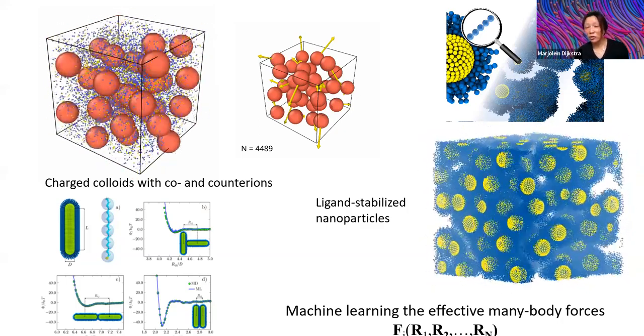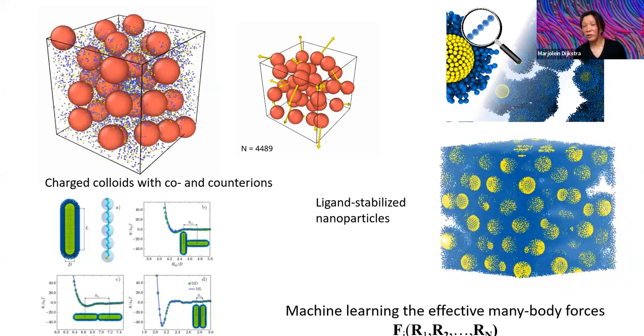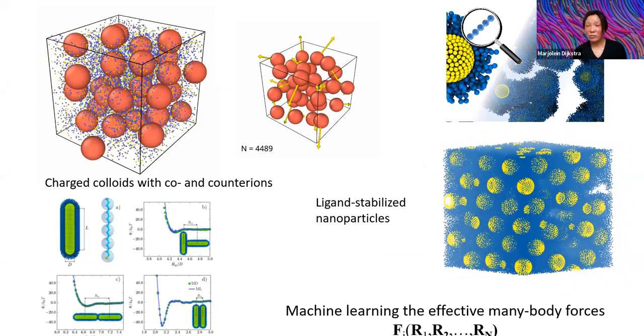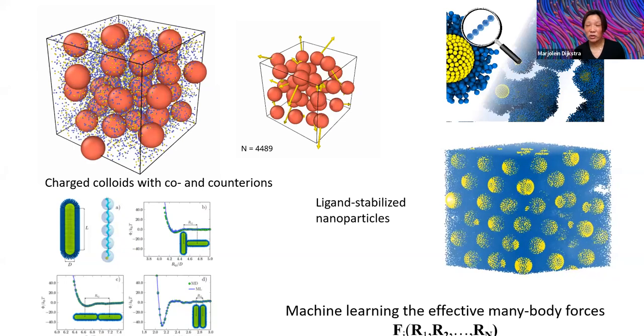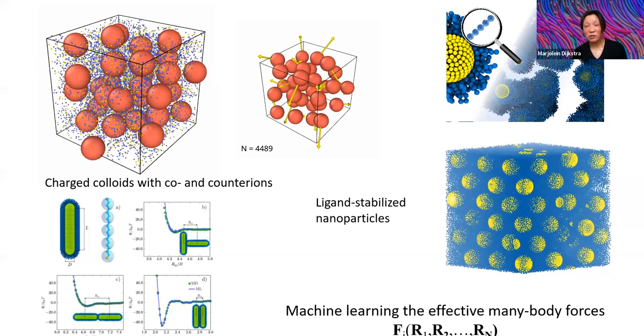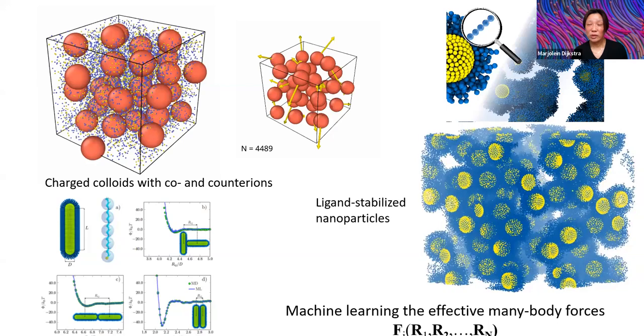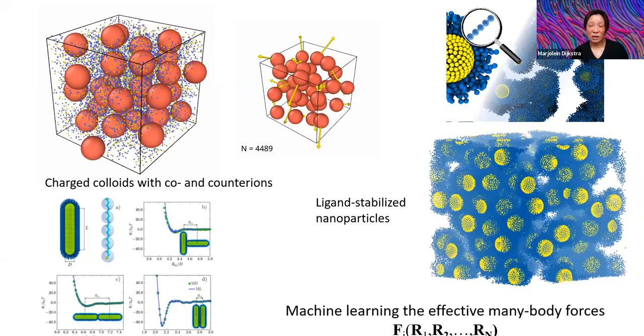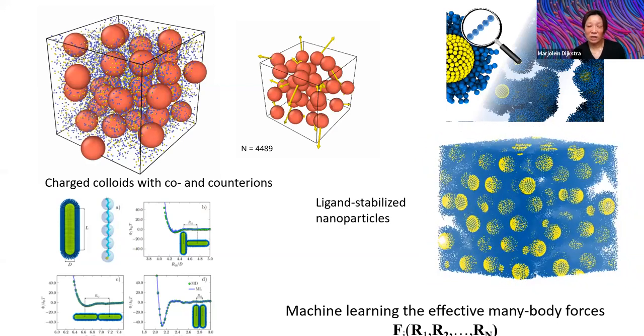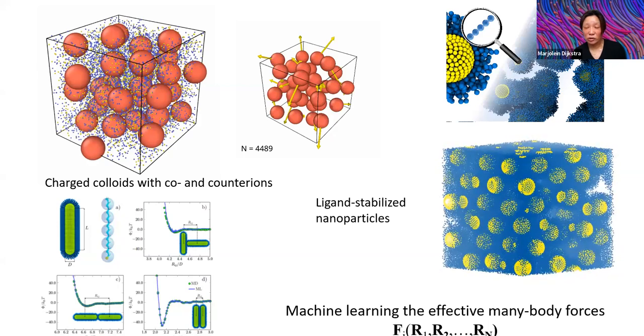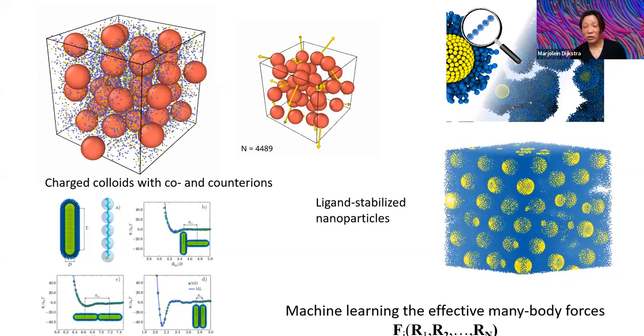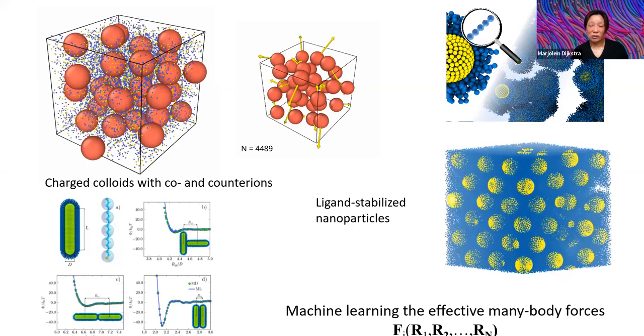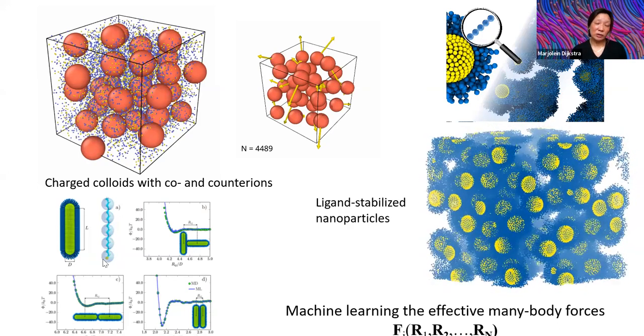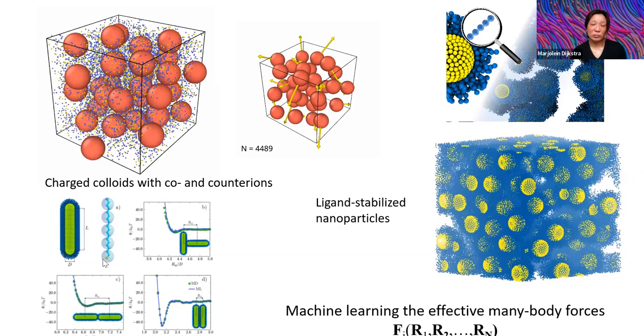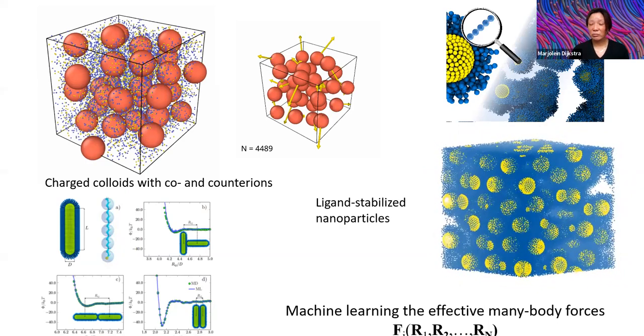We also apply it to ligand stabilized nanoparticles, where the particles are stabilized by ligands on their surfaces. Also, this is extremely time consuming to simulate all the time. But also here we can basically machine learn the effective many body forces, which we calculate from molecular dynamics simulations. And we also are extending it to anisotropic particles and surface patterned particles.